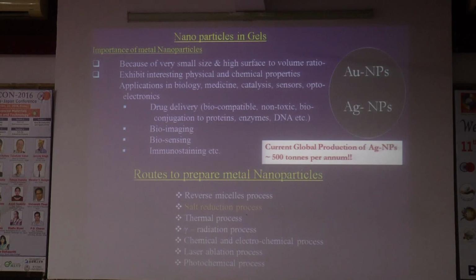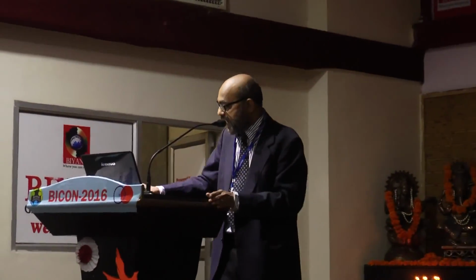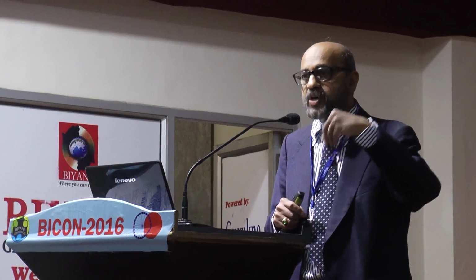Now we have also done nanoparticles in gels. We have put nanoparticles in gels for catalytic applications, and I would like to show you one example that is very simple. You simply take these gels and put them in a gold chloride solution, take out the gel, which absorbs the gold chloride salt, and put it in a reducing agent. Then you can make nanoparticles of gold in the hydrogel matrix, and this hydrogel matrix can be used for catalytic applications.